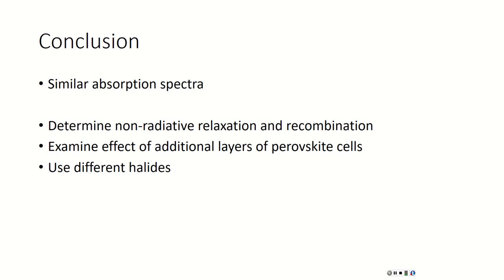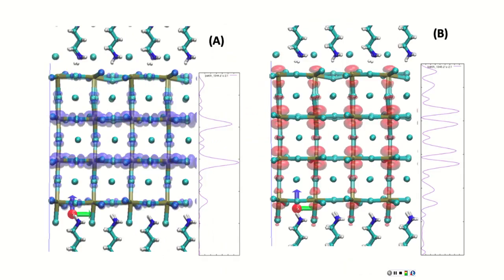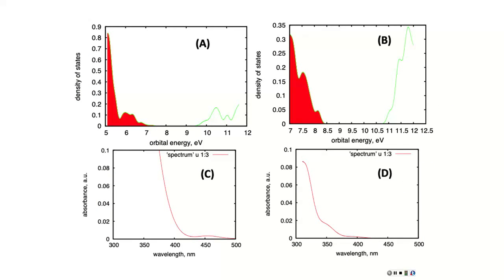Yeah. Can you go back to your density of states? I noticed it looks like B is a larger gap. B does have a larger gap. It was approximately a 2.8 eV gap for the Ruddlesden-Popper phase, where the hybrid had approximately a 2.3 eV gap.